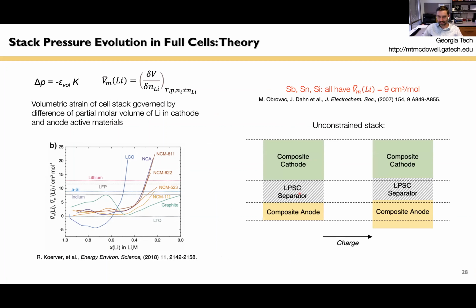And the basic idea is that in the discharge state, you have your cathode and your anode like this. In your charge state, your cathode decreases in volume a little bit, but your anode increases in volume a lot. So this is like the non-quantifiable way to say this. The partial molar volume of lithium is larger in the anode than the cathode. And so you have an overall volume increase of your stack. And in this constrained cell environment, this results in an increase in pressure. And that's what we measure. And this is why this is happening.